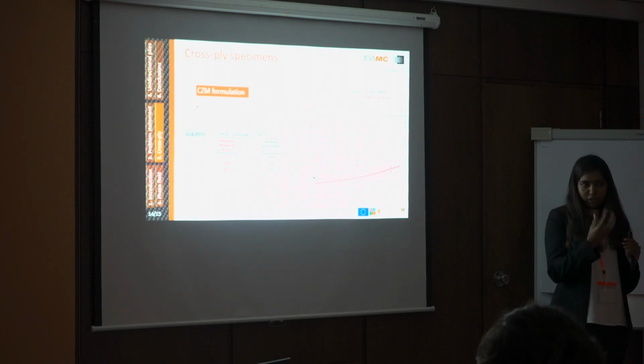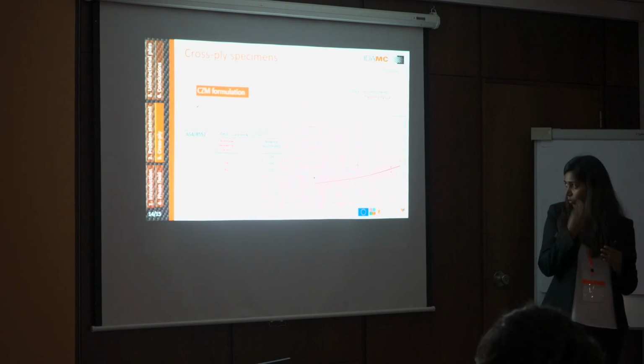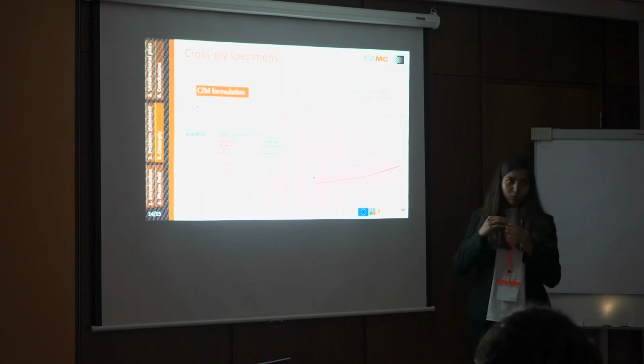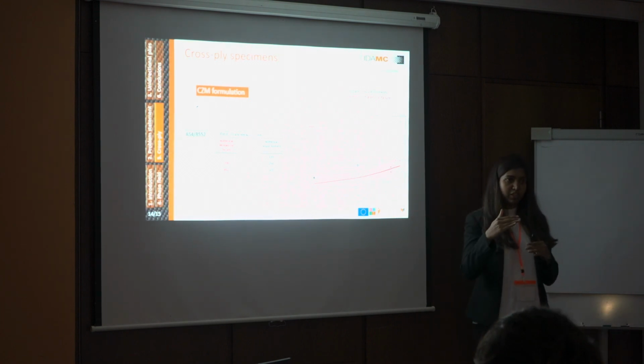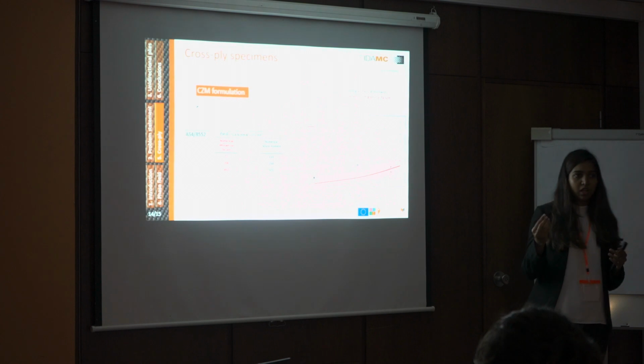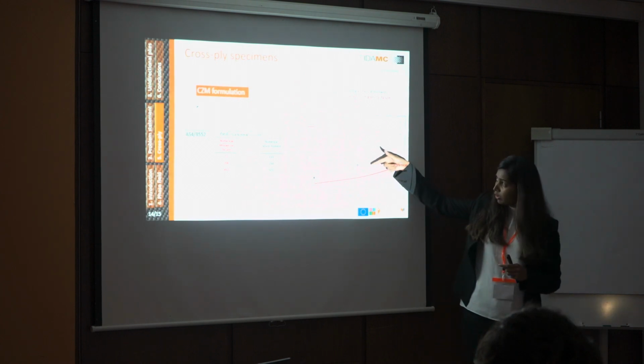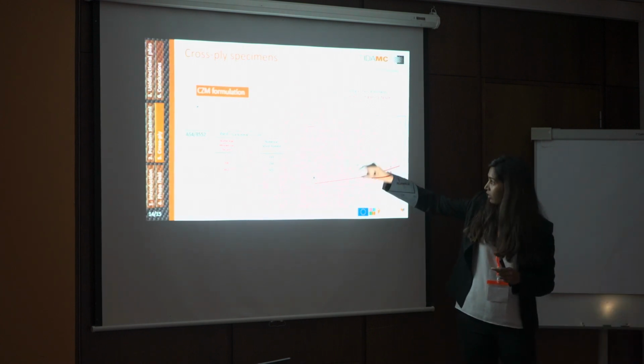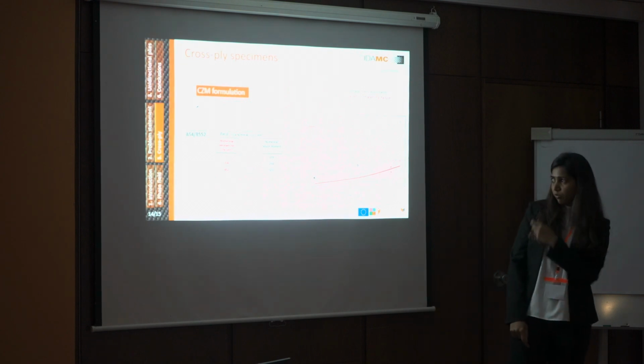So by changing the values of the tensile strength, it is very much likely for us to obtain a very good correlation with the damage initiation values because it is strength driven. But if we look at the failure moment values, we have this tiny difference here with the cohesive zone formulation.